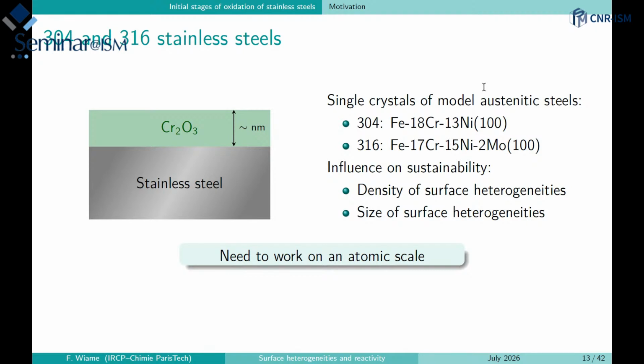If we want to understand how stainless steel is protected from corrosion, we should know that, in fact, very fast, there is a nanometric chromium oxide layer which is formed at the surface. This is generally how corrosionists are explaining the quality of resistance to corrosion of stainless steel. But in fact, this view is clearly too simple, because if we are looking at the surface and the oxide layer, there are many heterogeneities which are changing this very simple view. And we need to understand what's happening at the atomic scale, really to understand how we differ from this very simple model.